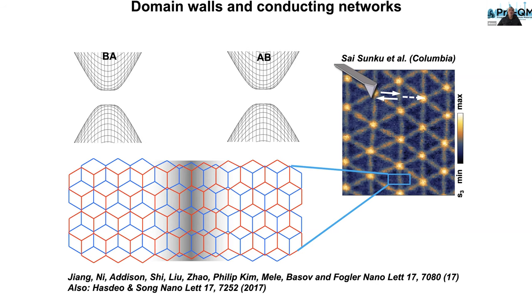So this is related to reconstructed electronic structure at the domain wall. This is the electronic structure of bilayer graphene. We work with heavily gated bilayer graphene. We need that to have plasmon polaritons in the first place. And it turns out that topologically these two domains, AB and BA, even though they don't produce obvious contrast here, are topologically distinct, and a very basic premise of topological band theory is that you cannot close this gap going from one domain to another. You cannot cross this boundary between one domain and another without closing the gap, and that's exactly what happens at the domain wall.